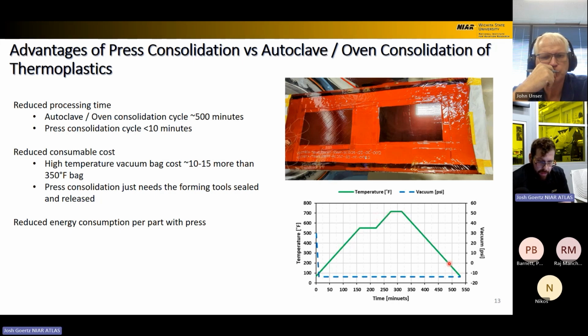This is one of our example thermoplastic cure cycles. As you can see, that's more than 500 minutes long. And with these PEEK thermoplastics, we're not getting automotive cycle times in our press, where every couple of seconds they're making a new part. But also in aerospace, you don't need that kind of manufacturing rate, so we're able to slow it down if we need to, and spend a little bit longer at temperature, build up the crystallinity and the material properties that we need, and still get a massive return on part rate versus autoclave type process.